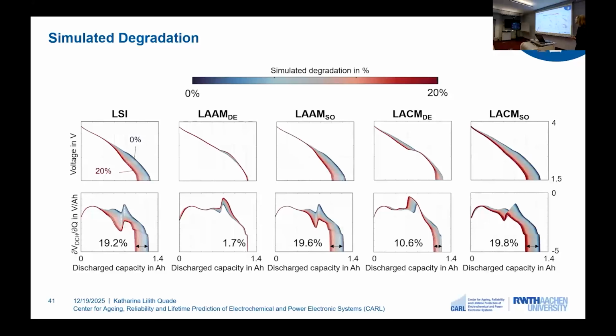And again, we can do this for all other degradation modes. And we can see very distinct patterns. We can see, for example, that for loss of active anode material in the desodiated state, this plateau becomes more pronounced with higher simulated degradation. And we can see that this results in a peak shift upwards. We can also see that this results in a very low capacity loss for the 20% simulated degradation. And we can also see the contrast, loss of active cathode material in the sodiated state, where we can see that this plateau is nearly disappearing completely. And this corresponds to a very high capacity loss.